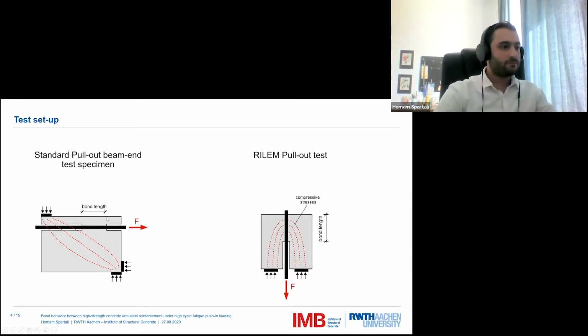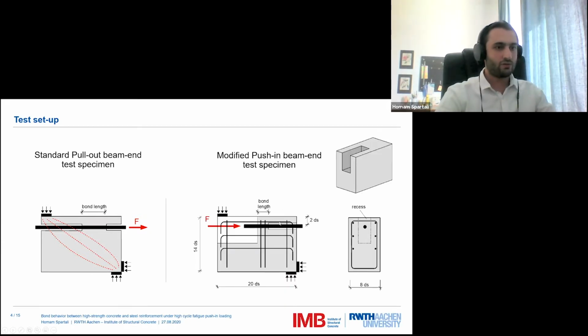But we have another problem here: in our case, we need to apply push-in loading from this side, and that could produce bending or buckling in the rebar in the case of the beam end test. So we had to introduce a void or a recess inside the body of the specimen so we can apply the load directly on this end of the bar. In this figure, we see also the reinforcement that we used, the concrete cover, and the dimensions of the specimen that were taken relative to the bar diameter, ds.